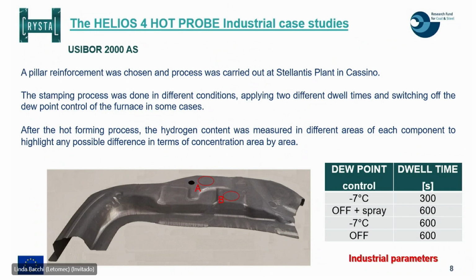The first one was on Usibor 2000 with the typical coating, which is aluminum silicon. We realized a series of components. In particular, we defined the A-pillar reinforcement, and we stamped these parts by making some variation in the stamping process. At Cassino plant, we were able to modify the dew point control by switching it off, and so also increasing the dew point inside the furnace, and we also varied the dwell time of the process.